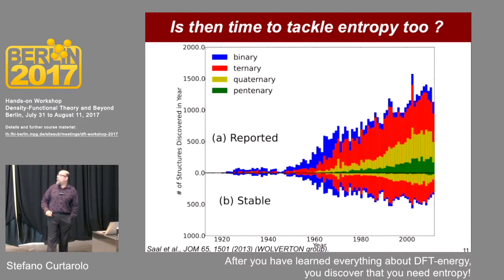In the past, a similar problem was identified. In fact, this picture does not come from me. This picture comes from the Wolverton group. They tried to replicate the stability of the ICSD entries with respect to, well, forget about the years, it's not important, the number of species. On the bottom are the systems that they are capable of reproducing stability for, and on the top, the systems that have been reported. So you see the blue over the blue is pretty much the same area, so they are able to reproduce all the binaries. The red and the red, you know, that's still okay. So they're able to say, well, that's stable from an enthalpy point of view.